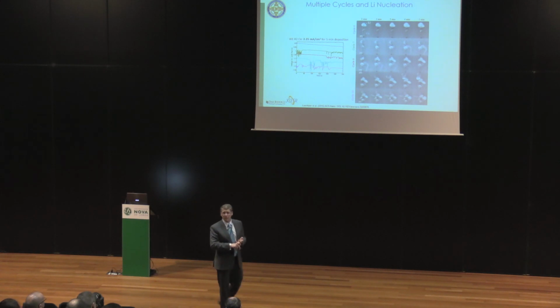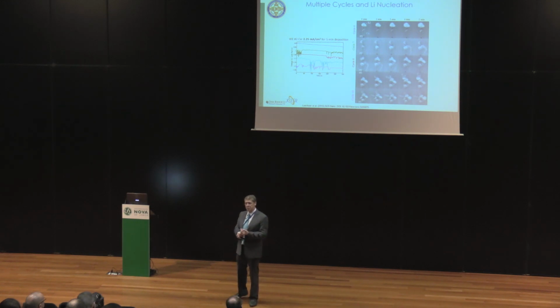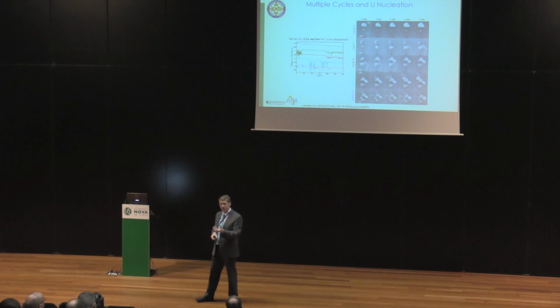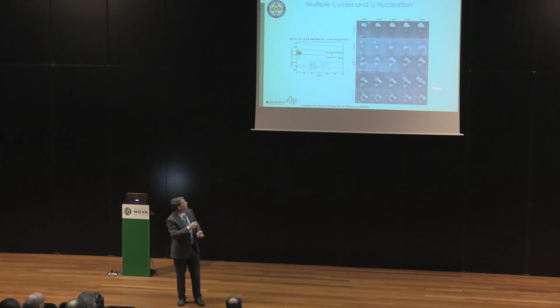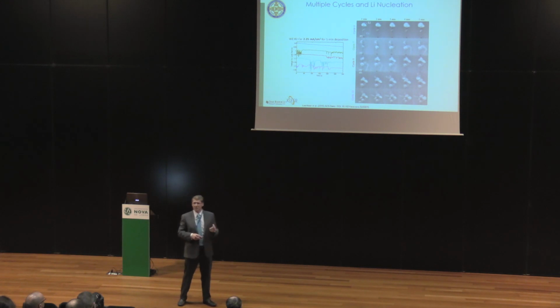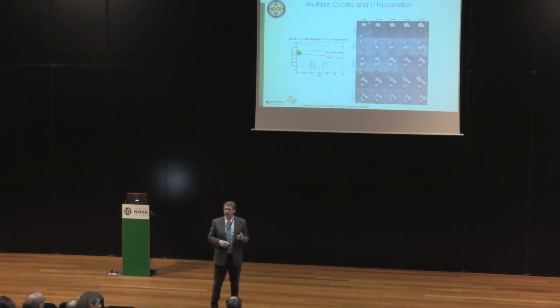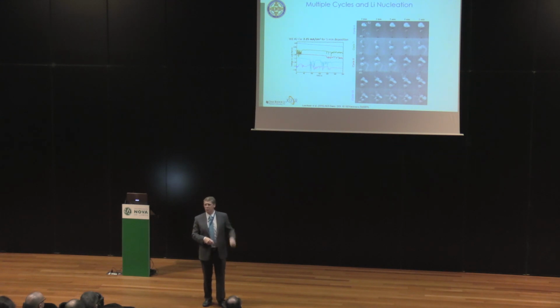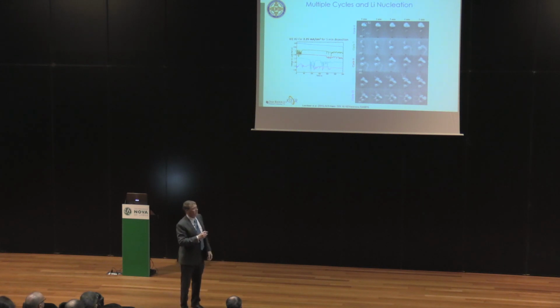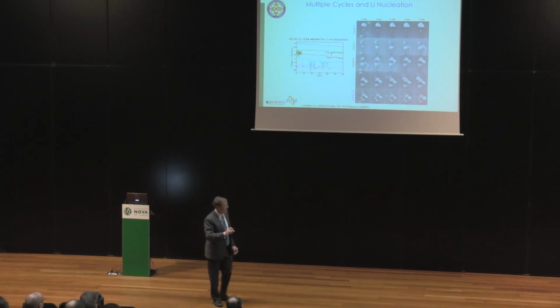But as we talked about, piercing of the barrier between the anode and cathode is an issue with dendrites. But there's also one other issue anytime you form a dendrite like this, or form a thick SEI layer, and that's lithium is part of that reaction, part of that material that's now caught in this SEI. And you can see it in the TEM, right? If it's showing as a light region, that's lithium that's locked up there. So that's lithium that you're no longer able to shuttle between the anode and cathode. So you're losing efficiency. It's a decrease in efficiency, and a decrease in the overall capacity of your battery. This is what Tesla is talking about with their 0.03% per cycle loss of energy storage capacity. So these dendrites or SEI layers as they thicken are an incredibly important aspect for us to be looking at, to see how we can reduce that.